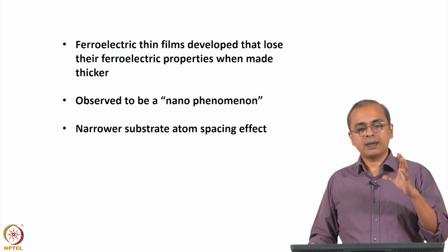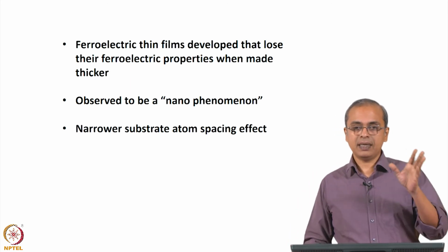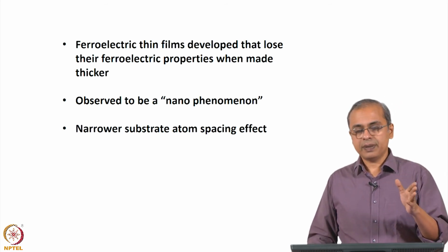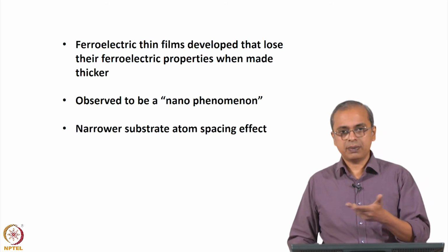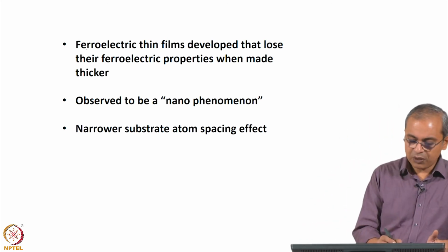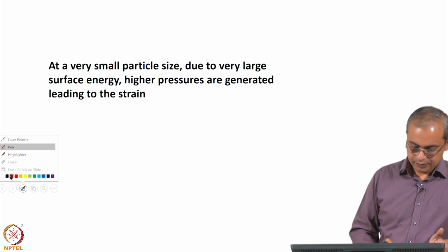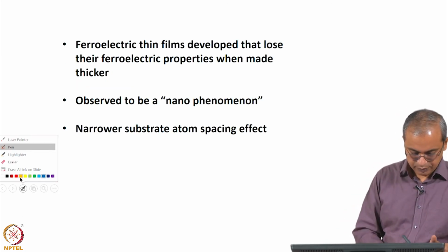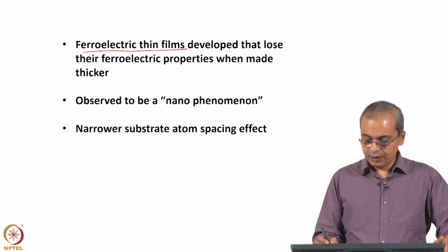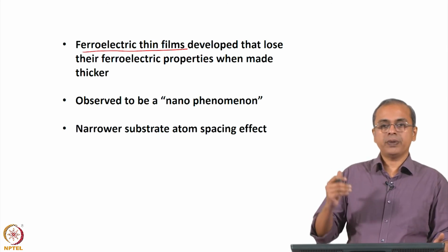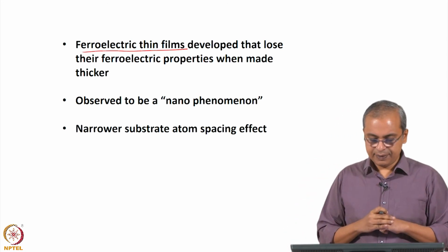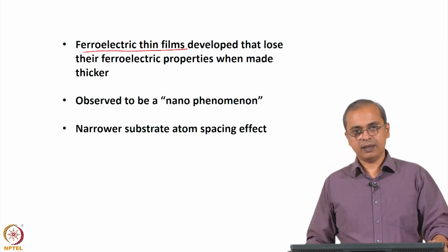But there was some more thought necessary to understand why this was happening in nanoparticles of this hafnium oxide based system. And just getting the particles is one thing, because you can do that with, let us say, ball milling and so on, but to do a controlled study to understand what is going on, another group has actually looked at ferroelectric thin films, to see if they can get their ferroelectric property or lose their ferroelectric property based on the thickness of the film. So, this way you have some control on the size and can see what is happening, and so some substrate is taken on which this film is deposited, and then they studied the ferroelectric behavior.